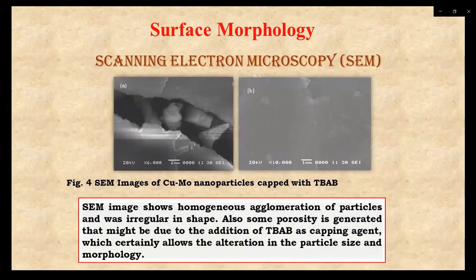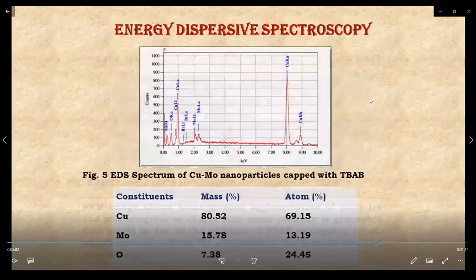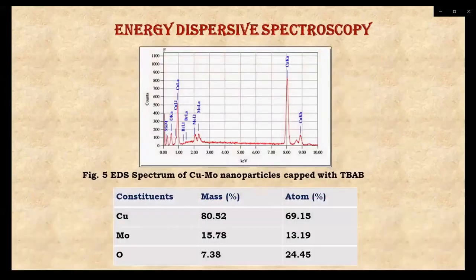To study the morphology of synthesized copper molybdenum bimetallic nanoparticles, we characterize it by the scanning electron microscope, which shows homogeneous agglomeration of particles and they are irregular in shape. The elemental data clearly shows the formation of copper molybdenum oxide bimetallic nanoparticles.